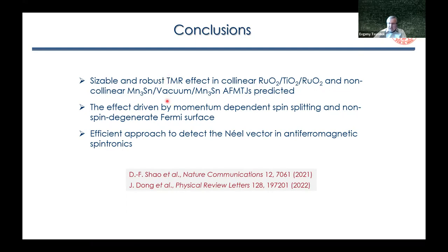Finally, the comment I would like to make is as follows. Obviously, in order to realize these effects, we need an additional ability to control the Néel vector. And this is very challenging, as you know. Especially for ruthenium oxide, which is a compensated antiferromagnet. It's easier to do for Mn3Sn because it has an uncompensated magnetic moment, and one can apply a magnetic field to switch the antiferromagnetic order parameter. But potentially, for both, we would like to have electric means, either electric current or voltage, to switch the antiferromagnetic order parameter. And this is challenging. More work needs to be done.